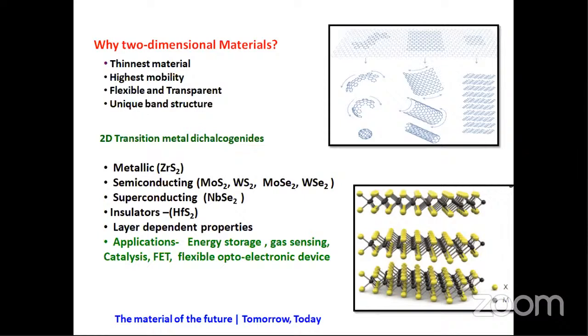In particular, I am talking about graphene. Graphene is a semi-metal with a zero band gap. Due to that, graphene has several limitations in electronic and photoelectronic devices. Basically, TMDCs exist with a variable band gap from 0 to 3 eV, which can be tuned by the thickness, defects, dopants, and also mechanical deformation, as we know very well, with the help of tensile strain and compressive strain.